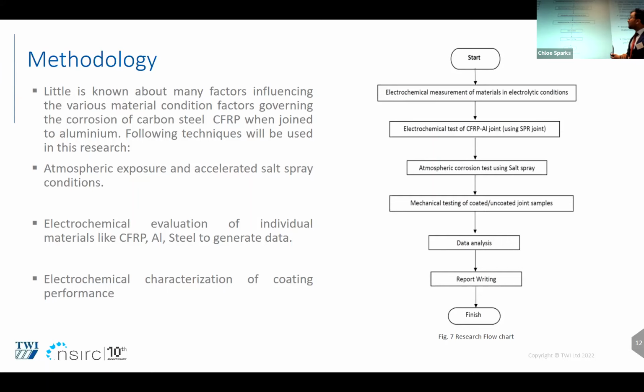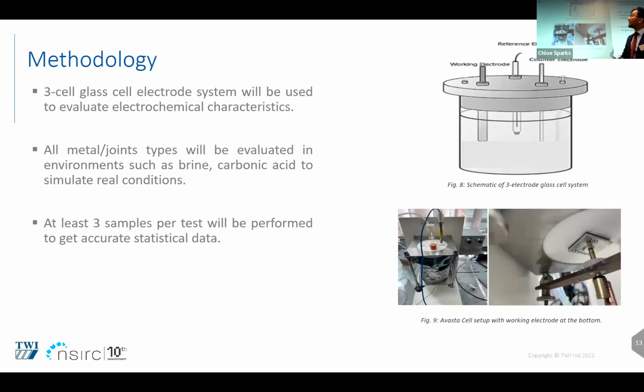This is the flow chart that I'm going to follow, the workflow chart. And this is the standard 3-cell glass electrode system. And this is the setup that I'm using to conduct the test for the 3 glass cell electrode. And this is my sample after the joint is made, and I'm using the Avesta cell. So all these metal joints will be evaluated in environments such as brine and carbonic acid. These are the solutions that will represent the real-condition environment that's been observed in the automotive sector. And at least 3 samples per test will be performed to get accurate statistical data.